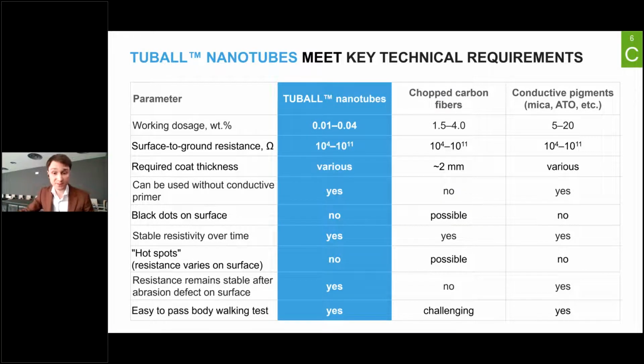And let's also compare single wall carbon nanotubes with another commonly used conductive additive, which is conductive mica, or similar alternatives like conductive ATO. It is a stable industrial solution which doesn't have the issues mentioned with chopped carbon fibers, but at the same time the working dosage of conductive mica is relatively high, and the cost performance is much higher than required. So such an additive can bring some additional limitation to your flooring business. With graphene nanotubes, with TUBALL, the working dosage and the cost performance is much better, and this leads, of course, to some additional cost reductions, which I mentioned before. So for the flooring area, it's a sustainable solution.